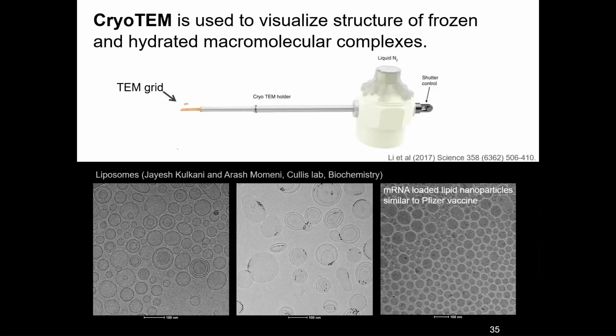So moving on to specialized applications, our 200 kV TEM can do cryo TEM. So samples will get frozen and kept at liquid nitrogen temperature. And we have a specialized cryo TEM holder. It has the liquid nitrogen dewar, so the sample is kept at cryogenic temperature all the time. A good example would be liposomes made of lipids, and lipid particles, if we dry them, they just don't keep their structure, like morphology gets totally distorted.